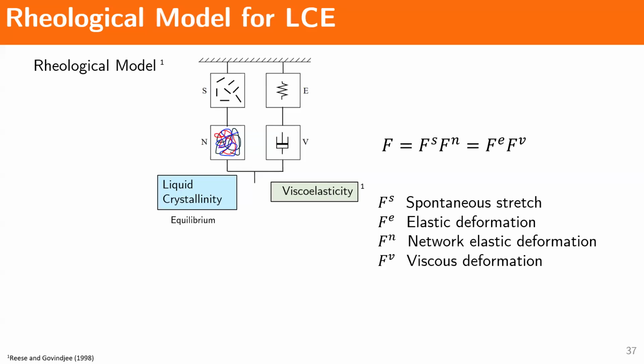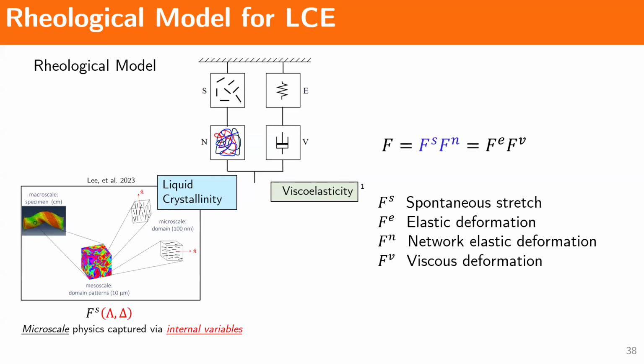The left branch is also called the equilibrium branch. This follows exactly the same model as before, so this is the true equilibrium, with no strain rate dependence, at time infinity, where this will take into account our nematic elasticity and our liquid crystals. This is where we take into account the microscale with the internal variables as before. And then on the right we have the non-equilibrium branch, which will take into account the viscoelasticity of our rubber materials. And we assume the following decomposition of our deformation gradient.